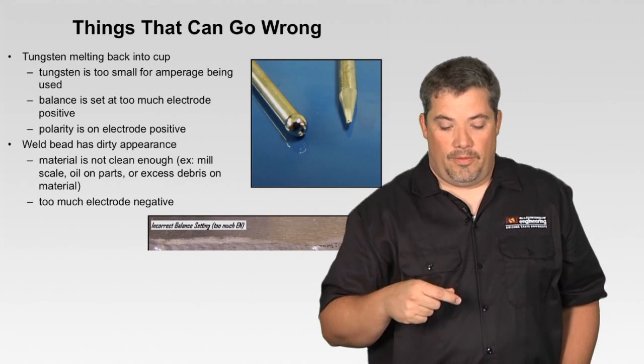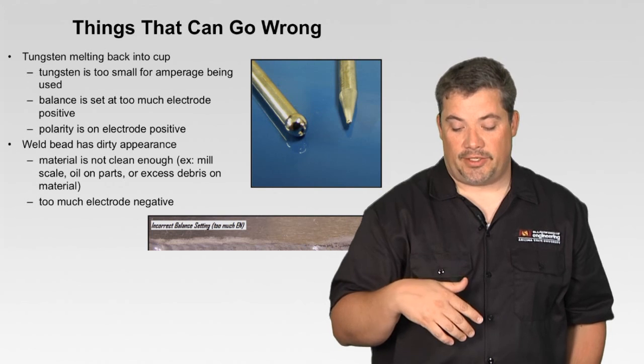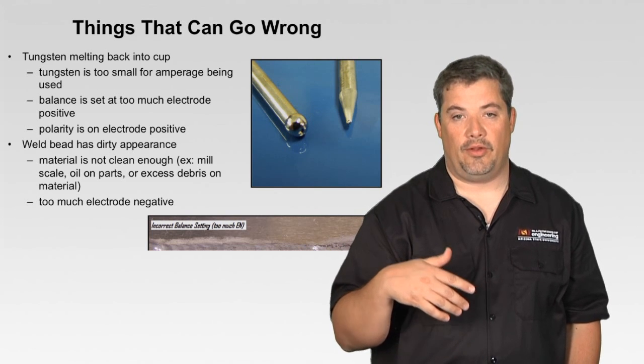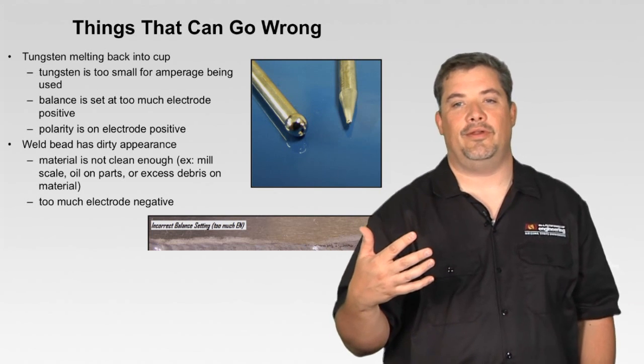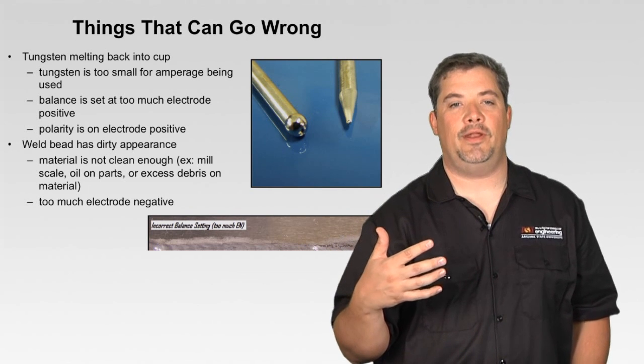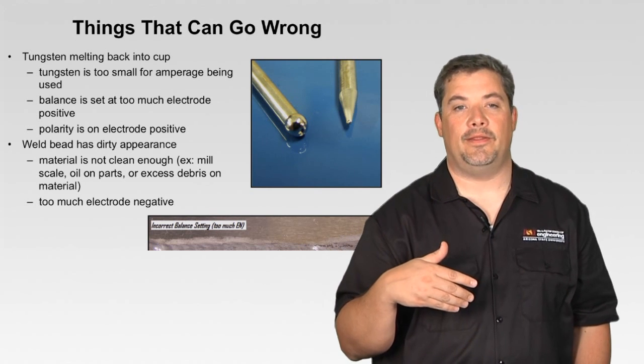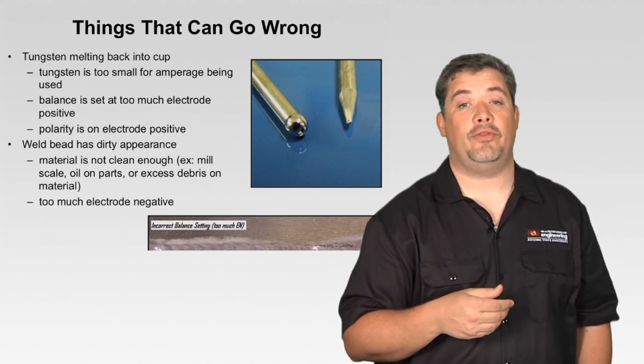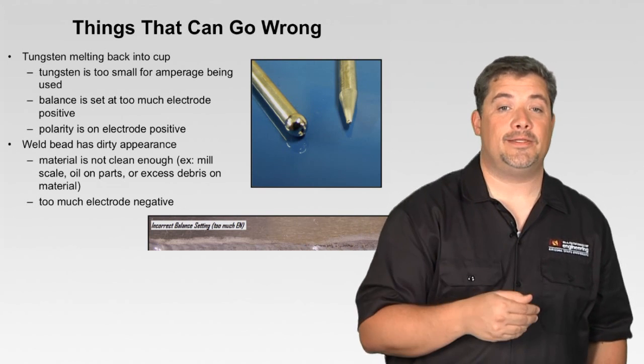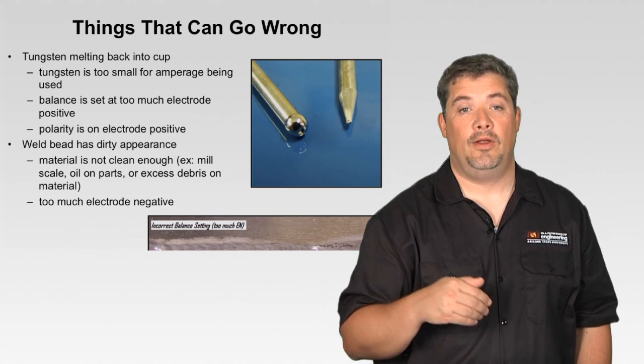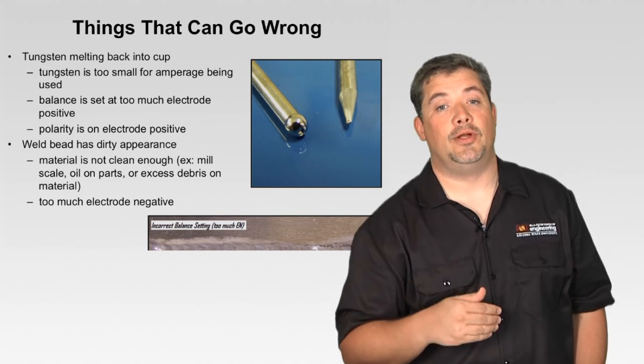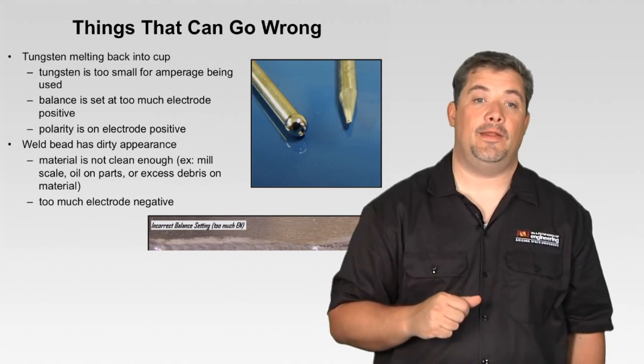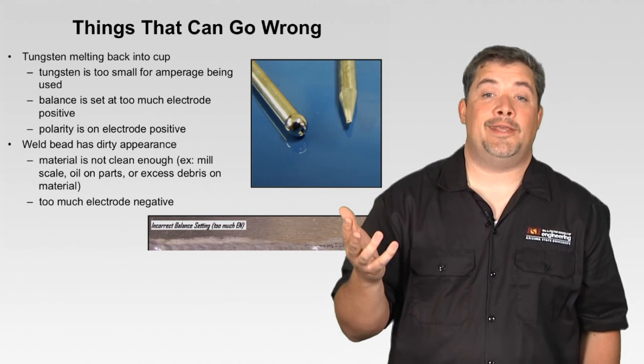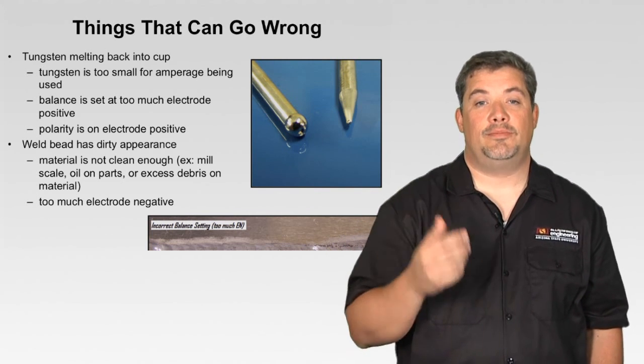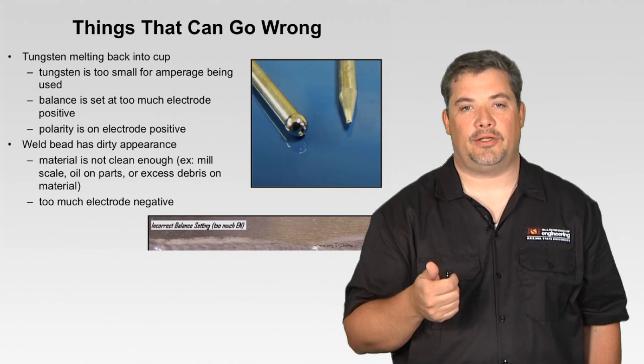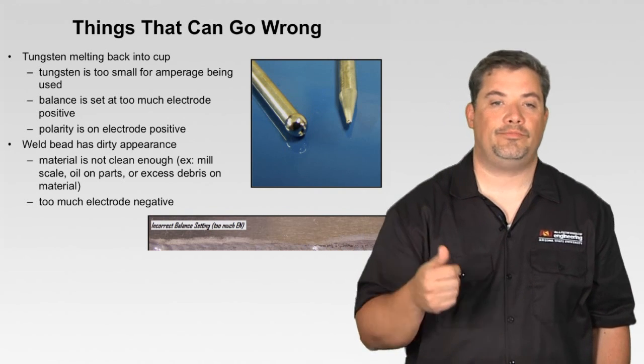Other things that can go wrong: here you can see an incorrect balance setting. Too much electrode negative may be a case where you have such a heavily oxidized material, you're not using enough electrode positive to help get rid of it. But that tungsten melting back into the cup means your tungsten's maybe too small for the amperage you're carrying. Maybe your balance is set to have too much electrode positive, or maybe your polarity is on too much electrode positive for your amperage on that side. Or maybe you just didn't go to AC by accident. So if that tungsten melts back into the cup, it's too much electrode positive some way or another.